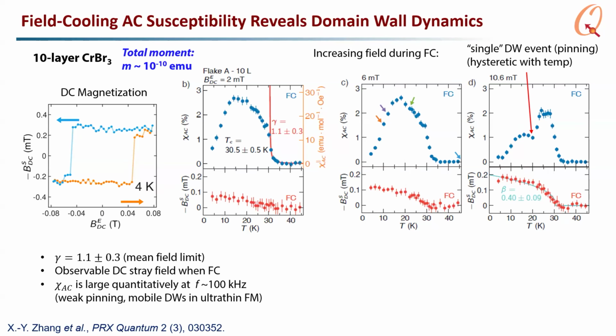This 10-layer flake has a very tiny moment, 10 to the minus 10 emu, just based on the size. We can measure the DC magnetization, and we can measure its AC susceptibility as we cool down in temperature across TC. We can measure it for different values of the field cooling field, the amplitude of the cooling field. So we're cooling it in different fields, and you can see that we can do DC at the same time as AC. At the lowest field, the DC magnetization is barely rising. It means it's forming a lot of small domains in the sample. Whereas at high field cooling, we see a strong rise in the DC field, so it's becoming saturated and forming only a single domain.